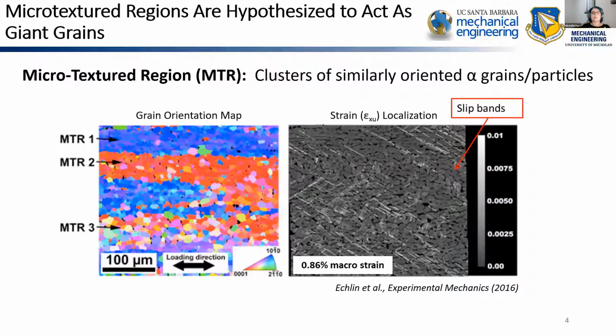And upon applying a tensile load to this sample and monitoring it via DIC and an SEM, they were able to see that they had slip that traversed through the entirety of the softer MTR, the blue, and then abruptly stopped at that hard-soft interface, supporting this belief that they have in the community that these MTRs sometimes behave almost like giant grains. So those longer slip lengths are going to create a larger dislocation pileup and thereby an even earlier crack nucleation due to the load shedding effect.